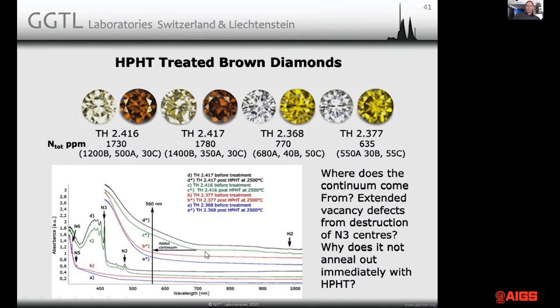And you can see what happened to the spectrum. The spectrum went from the N2 and N3 center spectrum into a continuum. But compared to what you see in trace A and trace B, the low N3 center samples, the high N3 center samples, you added a continuum on top of the regular C center continuum down here. It starts about 700 nanometers and goes all the way to the visible. And this added continuum is responsible for the brown color in these stones. Now the question is, where does this continuum come from?